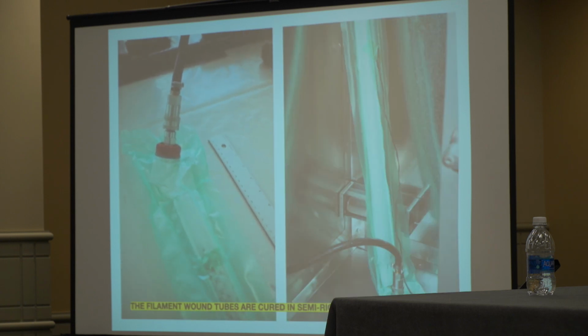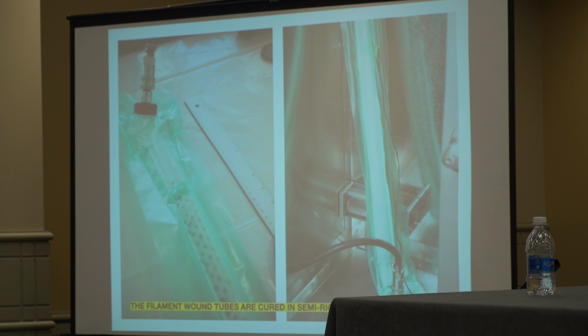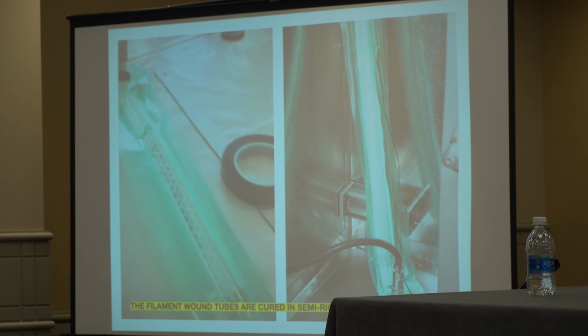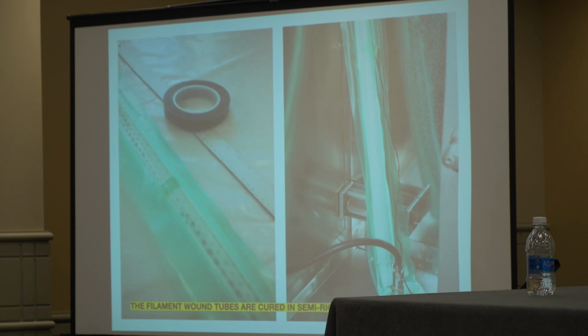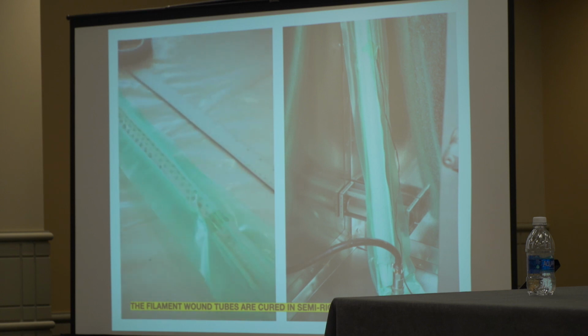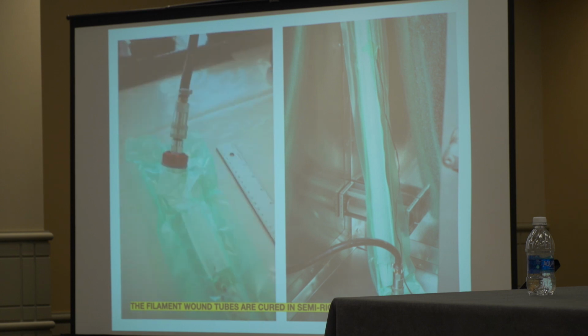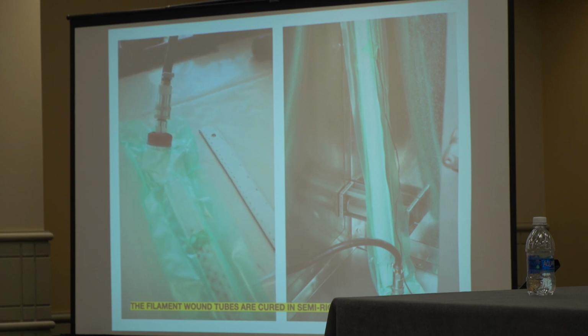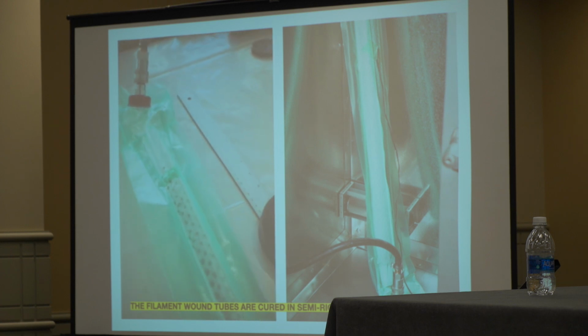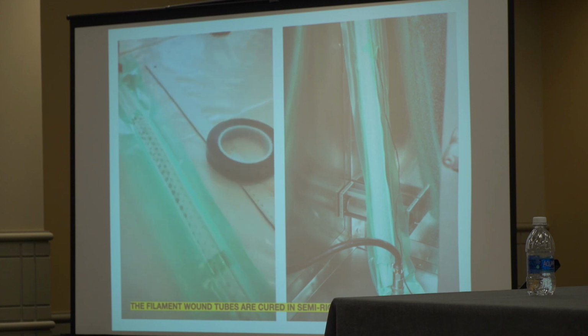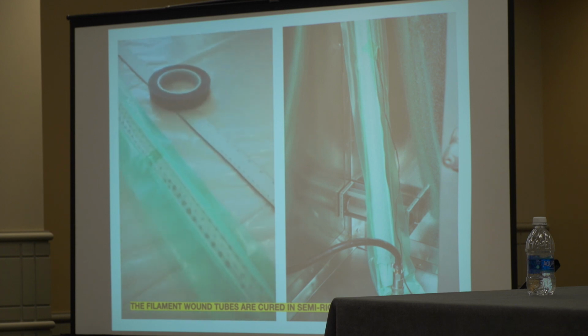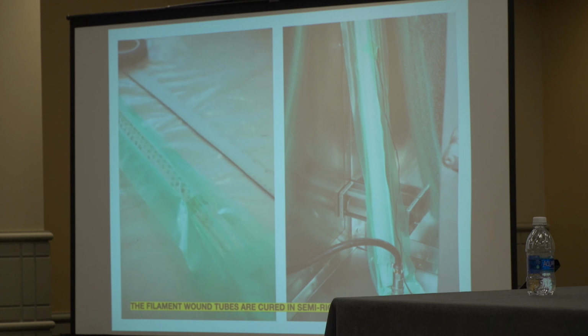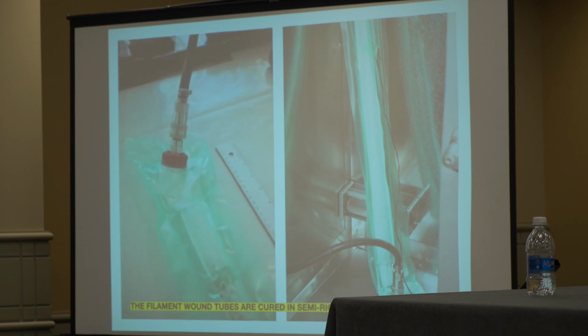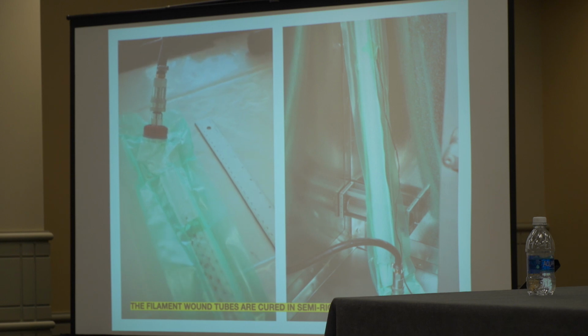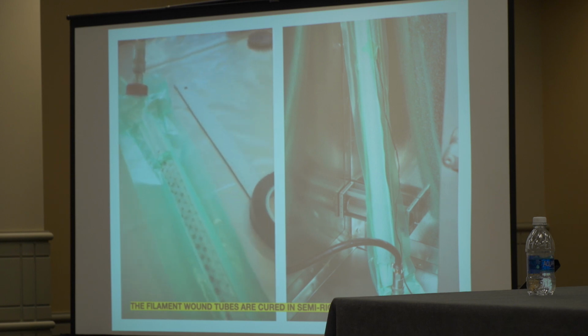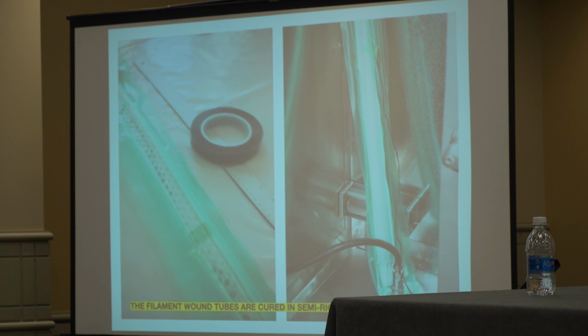And so this is the bagging and curing process. On the left there is a vacuum bag that's made in the shape of the tube, a little bit of breather, and those little spots there where the excess resin is getting sucked out of the layup. On the right here is the tube actually being cured in an oven. The tubes cure for about 4 hours after they're wound. The oven is like a proofing oven. The temperatures are pretty low because I'm using thermoplastics, so they're curing at about 120 degrees depending on the part.